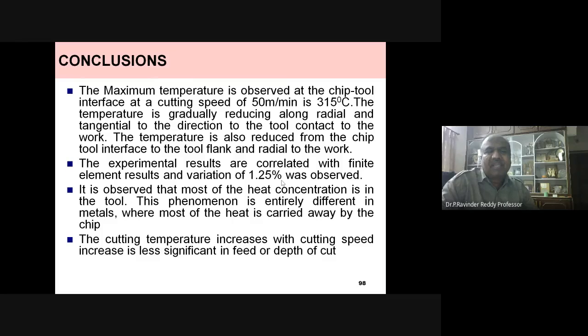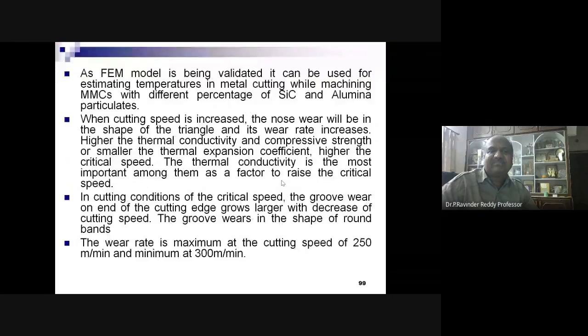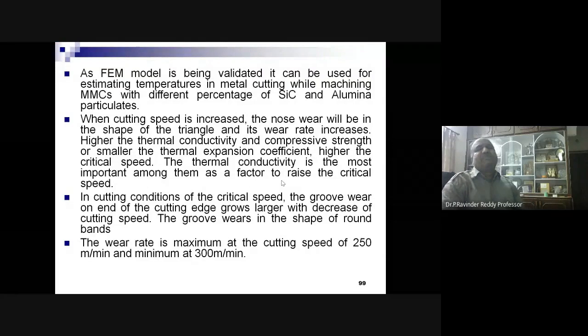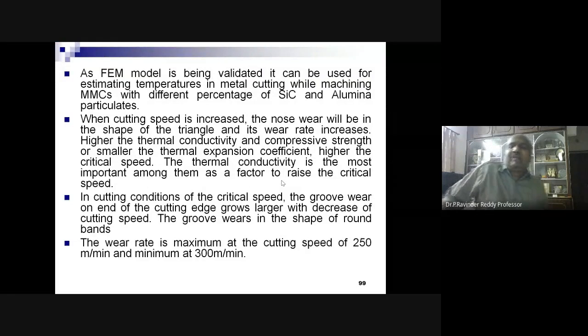is 1.25%. It is observed that most of the heat concentration is in the tool. This phenomenon is entirely different in metals, where most of the heat is carried by the chip. The cutting temperature increase with cutting speed is more significant than with feed and depth of cut. As the FE model is validated, it can be used for estimating temperature in metal cutting while machining MMCs with different percentages of silicon carbide and alumina particulates.